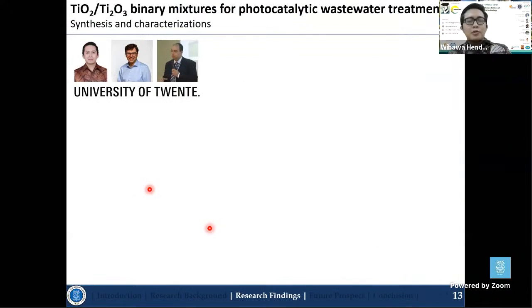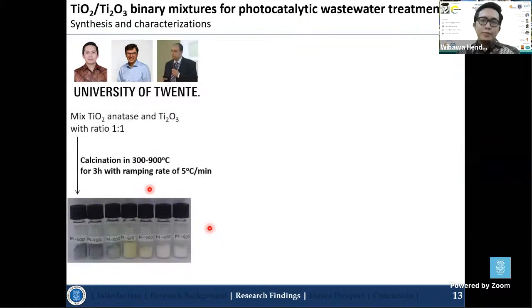So in my research during my master program, I did 2 methods in order to introduce defect sites in titanium dioxide catalyst. So the first method is just physical mixing of titanium dioxide with the titanium trioxide with the ratio of 1:1, and doing the calcinations from 300 until 900 degrees C for 3 hours. So interestingly, it seems that the color is changing by increasing the calcination temperature from the grayish color to yellowish color, and finally at the higher temperatures, it will produce white color of the powders of the mixtures.